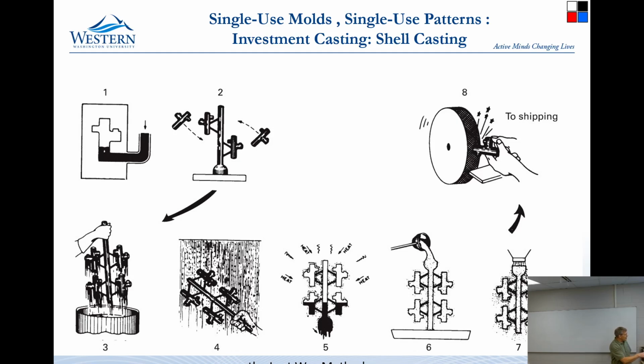You take those little wax parts and you attach them to a sprue that is also made of wax, and you add runners in there. When you put this all together, this is called a tree. So this is all wax material. You take it and you dunk it in a ceramic slurry, and then you shower it with ceramic particles, and you do this back and forth a whole bunch of times. And then you hang it upside down and heat it. This both cures the ceramic and also melts all the wax out of the inside.